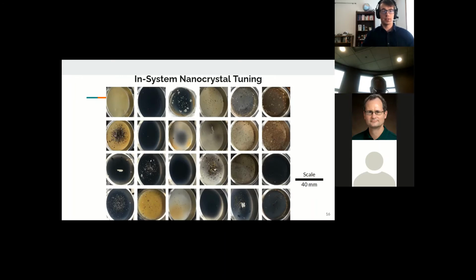This figure on slide 16 displays some of the first powders made in the reactor. You can see there are some flakes in some of the powders that were created. The flakes were the result of doing multiple runs in the same reactor without cleaning it. These flakes were avoided in the characterization of the powder as they weren't consistent. The runs that composed the flakes would be difficult to reproduce in a meaningful way. But despite this fact, the flakes could be potentially attractive as a future study because they exhibited some photoluminescence, whereas the rest of the powders did not exhibit photoluminescence.